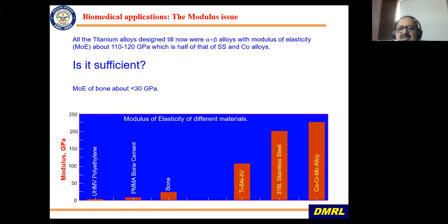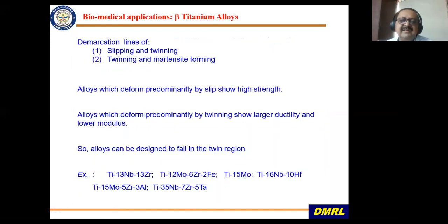So there are new titanium biomedical alloys that are being discussed. Here I have shown the modulus of cobalt chromium alloy, which is a biomedical alloy, stainless steel, which is also used, Ti6Al4V, which is still used as one of the implants, and then another new beta alloy, Ti-35Nb-7Zr-5Ta. As you can see, it has got much lower modulus, approaching the modulus of bone. And these alloys, that is why, are becoming famous. The design depends on whether you can have your composition so that you can have twinning and martensite formation, then you can have this lower modulus. That is what people have realized. So there are a host of compositions which people have come up with for biomedical applications, but it is seeing use, though not exactly used widely till now.